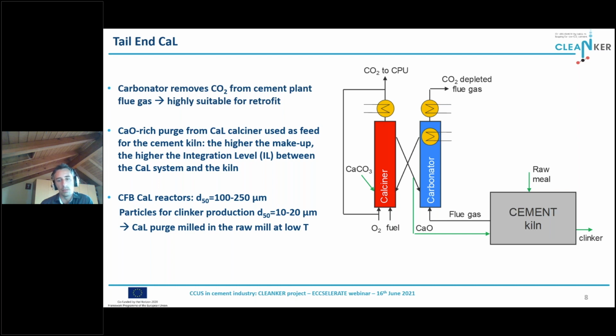The higher the makeup within the calcium looping process, the higher the integration level between the capture process and the system. Since this system is the more conventional calcium looping one, it is based on circulating fluidized bed reactors. For this reason, the particle size is higher than the size of the conventional cement raw mill, one order of magnitude higher. So the sorbent purge, before being fed to the preheating tower and to the kiln, in general has to be milled in a cement raw mill at low temperature and then heated up again within the kiln process.